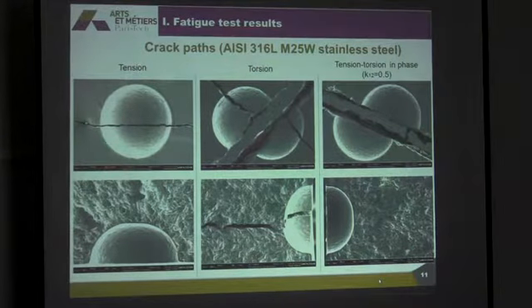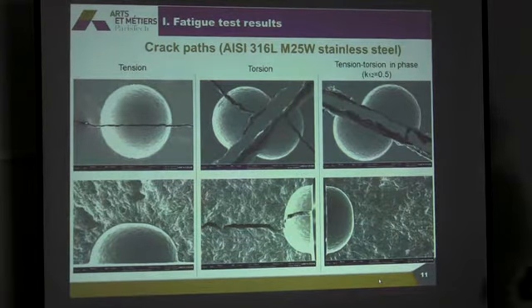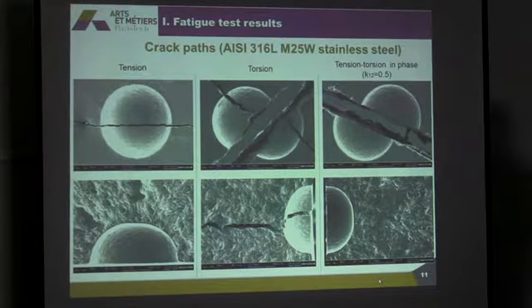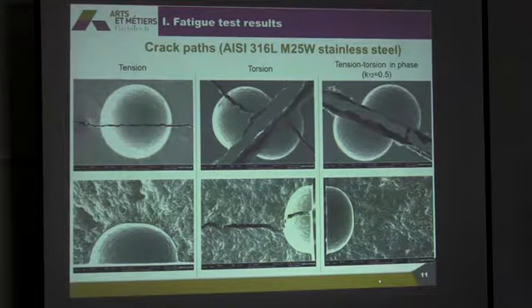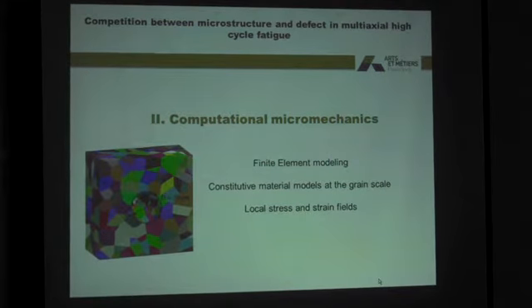If we look now at the crack path in tension, torsion, and tension-torsion in phase, we see that the crack propagates on the plane of the maximum principal stress. I'm not talking about the initiation — I will talk about the initiation later in my talk. So I have some macroscopic data from this experiment.